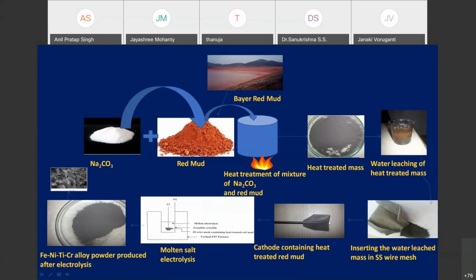Then we have connected it to the current collector of the stainless steel rod, and we have carried out the electrolysis. After electrolysis, the material is recovered from the basket and water washed. And after water washing or acetone washing, we are getting this kind of FeNiTiCr alloy powder, produced mostly in the powder form. In this electrolysis process, whether you take it in the compacted form or the powder form, mostly we get the powder form. Sometimes some sintering may happen due to the high temperature, or if you increase the electrolysis time. But here, particularly for the red mud, we are getting this kind of FeNiTiCr alloy in the powder form.